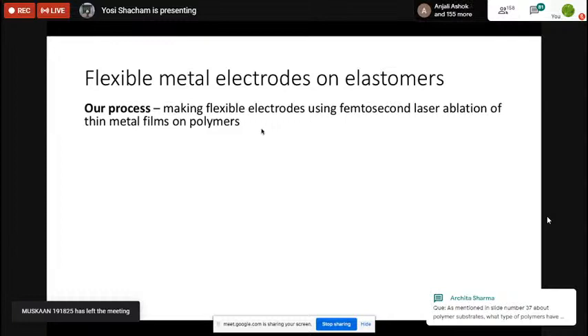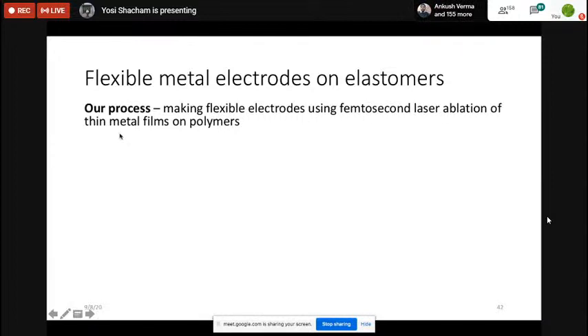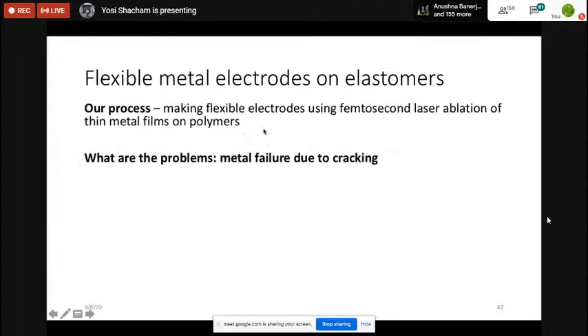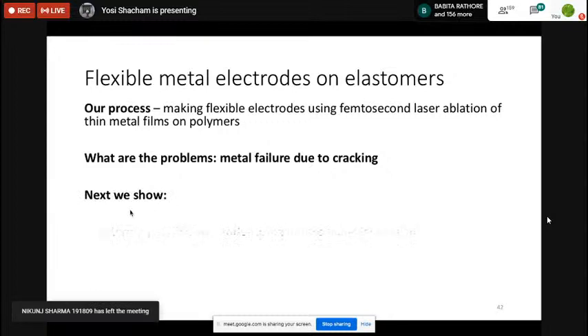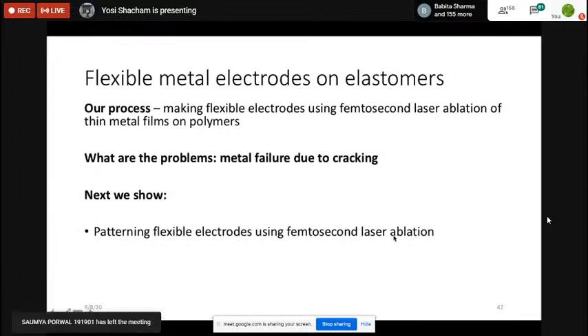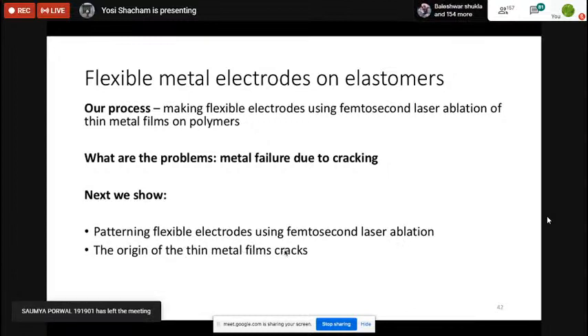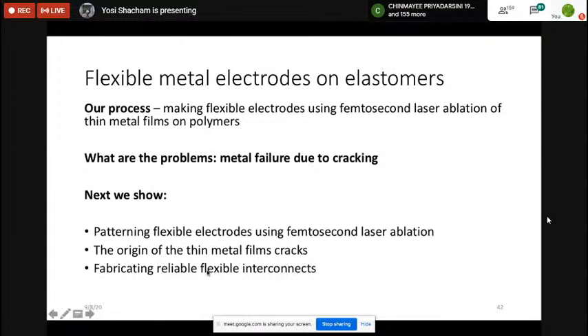So our process, which we developed at Tel Aviv University in collaboration with the University of Milano, is flexible electrodes using femtosecond laser ablation on thin metal films on polymers. I'm switching from the large overview of the field, where I gave 35 minutes of review of flexible electrodes and described all the materials. In the next 20 minutes, I'm going to talk about what we do and how we solve the problems. One of the biggest problems that everybody faces is metal failure due to cracking. Next we show patterning of flexible electrodes using femtosecond laser ablation and the origin of the crack. I will explain why there is cracking and how to avoid the cracking, how to make reliable sensors.